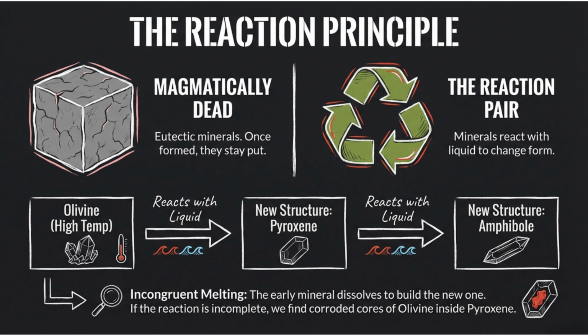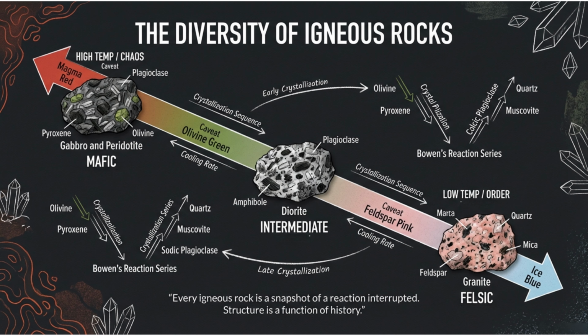For example, high-temperature olivine can react with the surrounding melt to produce pyroxene. Pyroxene, in turn, can react to produce amphibole as the system evolves. If these reactions go to completion, little evidence of the original mineral remains. But if the transformation is incomplete, we can find corroded olivine cores preserved inside pyroxene crystals, physical proof of the chemical upgrade that was underway but not finished. These reaction textures provide a window into the dynamic, non-equilibrium nature of magmatic systems. Every igneous rock is essentially a frozen moment in an ongoing magmatic reaction.